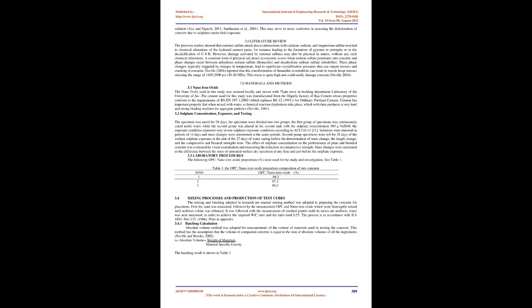According to Skalny (2004), concrete can be vulnerable to damage when salt crystals grow from a supersaturated solution in its pores. This process was described as physical attack on concrete since, unlike chemical sulfate attack, it does not involve any chemical interaction between the sulfate ions and the concrete hydration products (Haynes et al., 1996). However, the consequences of physical sulfate attack are different from those of chemical sulfate attack since it leads to surface degradation similar to that caused by cycles of freezing and thawing.